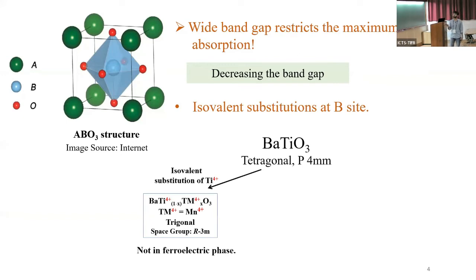For the present study, we chose barium titanate as the host material, which exists in the tetragonal phase at room temperature, having the P4mm space group. Now, let's say one does an isovalent substitution of manganese 4+ for titanium 4+. This substitution leads to a phase transformation from tetragonal to trigonal, and therefore to the centrosymmetric space group R3̄m, which is no more ferroelectric in nature.